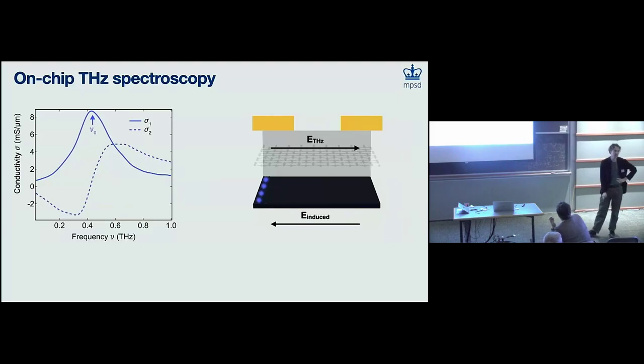James, I also have a question. Shouldn't a plasmon give you a Drude response? Because if you see a Lorentz oscillator displaced at a finite frequency, that indicates to me that it should be some kind of phonon or something. No, it's definitely a plasmon. I'm not disagreeing with that, but if I just take an epsilon of 1 minus omega p squared over omega squared, I'm going to get a Drude peak. If I just take my basic solid state textbook, I'm going to get a Drude peak. That comes from the plasma.